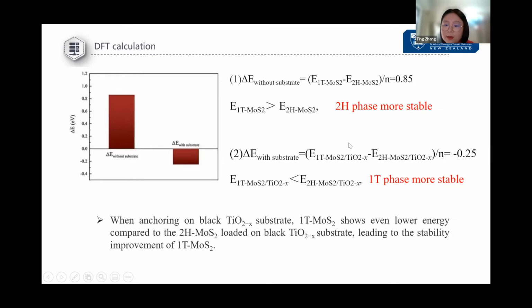But after they docked on the black titanium dioxide substrate, the 1T-MoS2 decorated on the black titanium dioxide substrate exhibits the smaller system energy. So we can make the conclusion that the 1T phase is more stable after the decoration of the black titanium dioxide, and it's even more stable than the 2H phase.